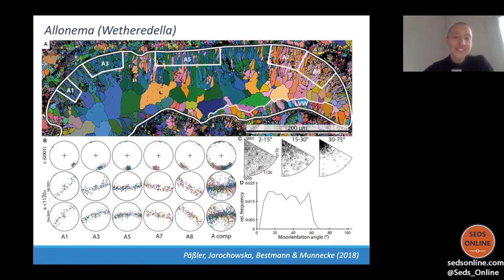So we see this kind of girdle structure where the individual crystals rotate around the C axis, and this rotation moves gradually as we go along the shell. So this is quite a constrained crystallographic texture. It is quite orderly. It is not something that we would expect in a microbial carbonate.